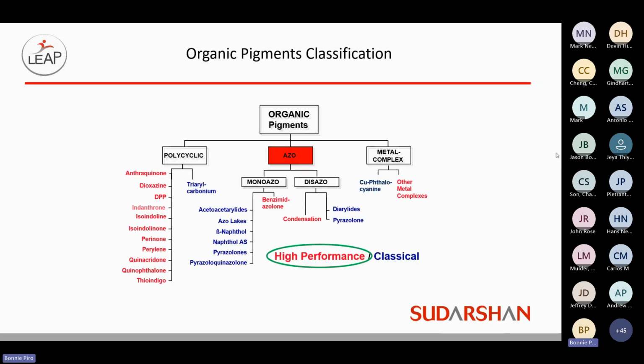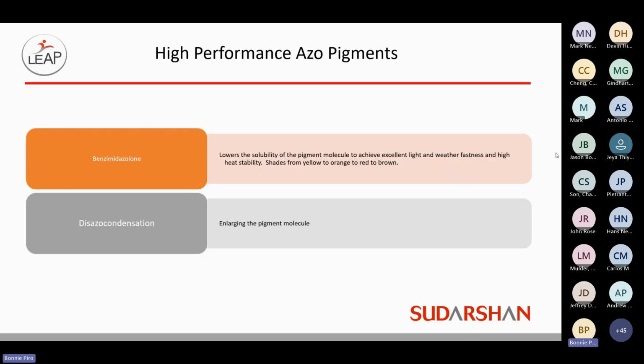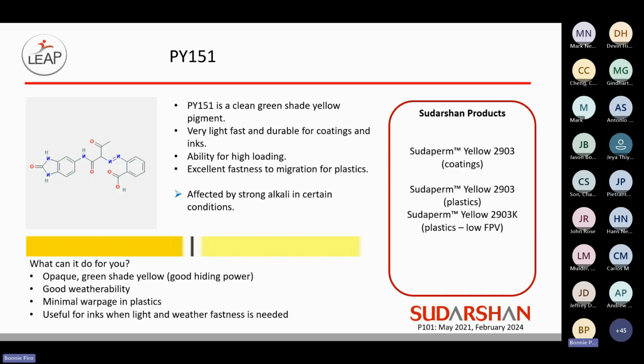Moving to the azo category, the benzimidazolones. The first one in the series is the Pigment Yellow 151. This is a green shade one, not quite as green as the Pigment Yellow 138, but it is pretty opaque, very durable for coatings and inks. And if you're looking for a high loading area, because it's a high particle size, it does allow for higher loadings. And it is good for plastics with respect to migration.